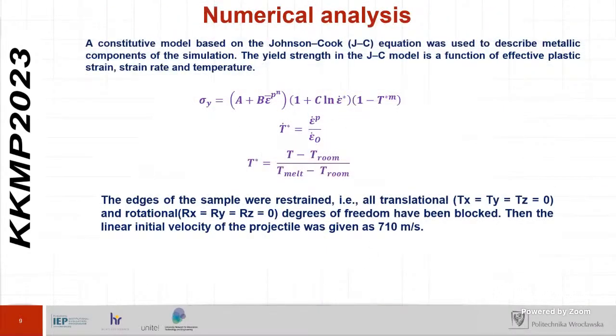And for the numerical calculation, because I'm considering metallic material, one of the models that is often used in literature, and has proven over time to be really valid and effective, is the Johnson-Cook model. We have this flow stress, which is equal to these parameters. However, for my own case, I did not consider the effects of temperature. It was not included here. And the plates were fixed in all directions such that there's no degree of freedom. In other words, there's no movement in all axes. It's fixed because this is how it should look in real life when you mount your sample before you fire the ammunition at it.